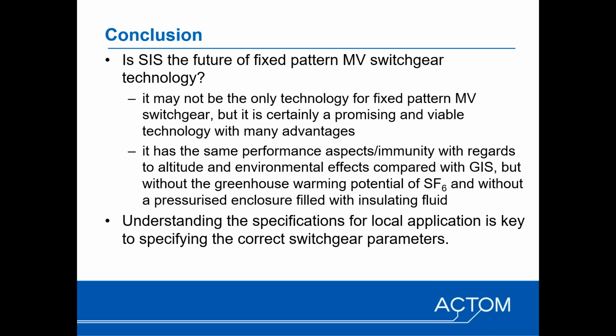And then in conclusion, is solid insulated switchgear the future? Well, it may not be the only technology available for fixed pattern MV switchgear, but it's certainly a promising and viable technology with many significant advantages, as I hope have become clear through this webinar. It has the same performance aspects or immunity with regards to altitude and environmental effects compared to GIS. GIS achieves this by virtue of the hermetically sealed, pressurized gas compartment, but solid insulation has the benefit of not having any global warming potential, GWP, as would be associated with SF6 and even some of the alternative gases, although they are much lower than SF6.